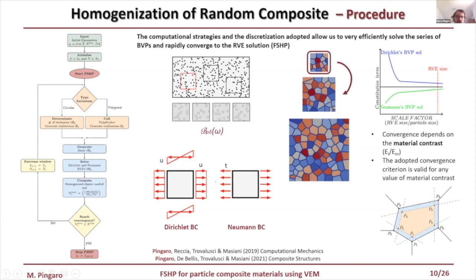Recently, the procedure has been improved to take into account polycrystalline inclusions with thin interfaces. In this case, we adopt PolyMesher, developed by Professor Paulino, as a tool for meshing the geometry. The idea is to generate an initial random Voronoi tessellation using PolyMesher, and after a shifting procedure, the interfaces between the grains can be created.